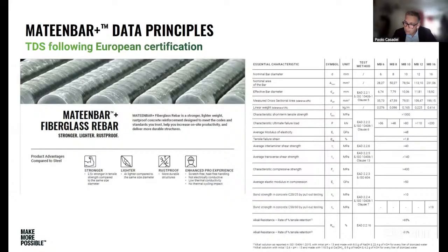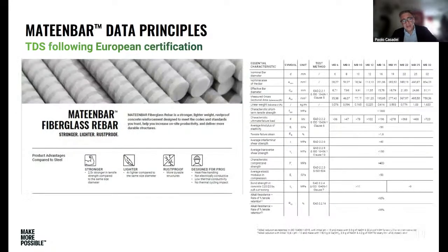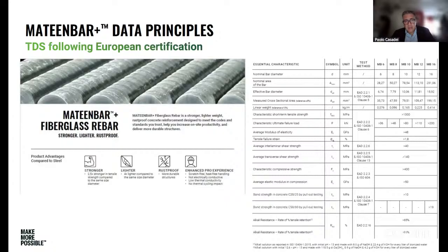One thing which is very important: on a job site, usually you handle steel, usually wearing gloves. Sometimes it happens that you take the steel bars with your bare hand. Now, in the case of GFRP bars, we need to be careful on that. We always need to wear gloves, because otherwise the bars leave very small spikes of glass, which may stick in our hands. It is not dangerous, but certainly not pleasant to have them in our hands.